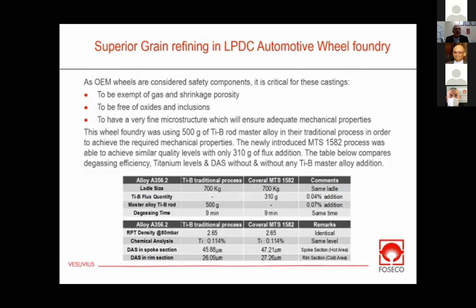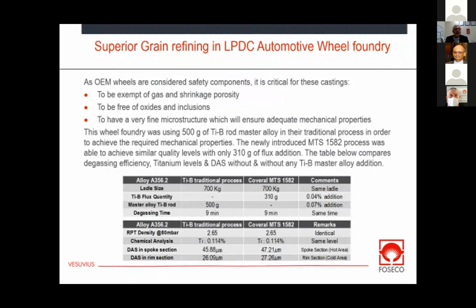Then the foundry cast some wheels. They took some wheels and looked at the density to make sure everything was comparable. They looked using the spectrometer at the titanium pickup, because they wanted to make sure that if they switched from a traditional Tibor master alloy to our product, the titanium pickup would be in the same range. You can see here, they had the same range.